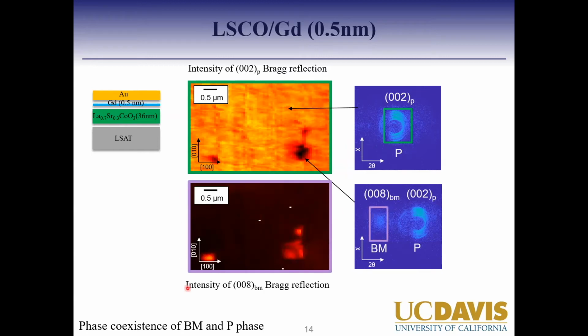So we first looked at gadolinium half nanometer. For gadolinium half nanometer, the intensity of this perovskite peak is orange and yellow, which is plotted here. We start to see some spots where we actually see intensity from the brownmillerite phase. If we integrate over these brownmillerite spots and plot that intensity, it's pretty much the opposite contrast. Wherever we are seeing perovskite deficiency, we start to see blobs of brownmillerite phase appearing. Okay, so that's the gadolinium half nanometer sample.